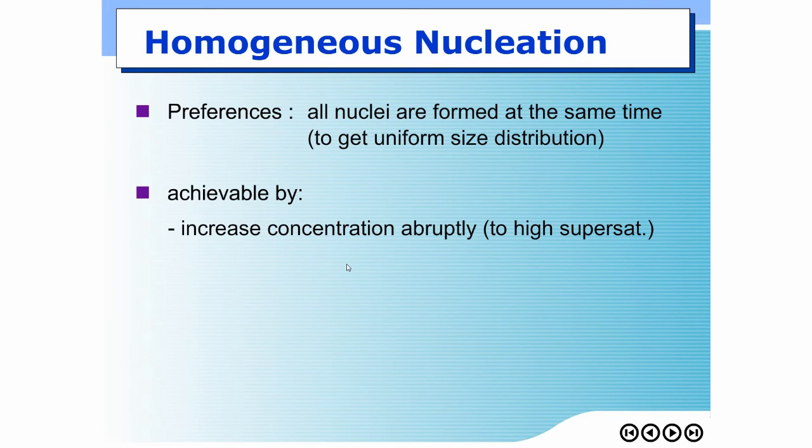If you slowly drop citric acid into the beaker, the reaction will start but progresses very slowly. The concentration of gold zero formed by the reaction would increase, but slowly, right? But if you dump all the citric acid into the gold as quickly as possible, then the concentration of the product would increase as quickly as possible as well. That's one way to do it.